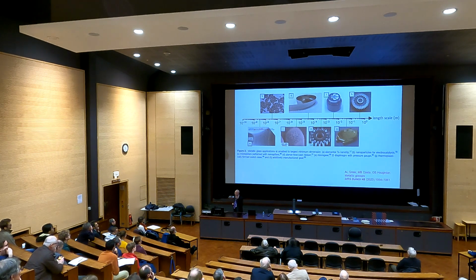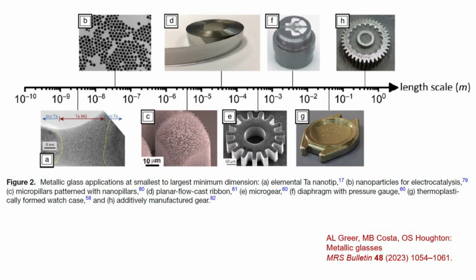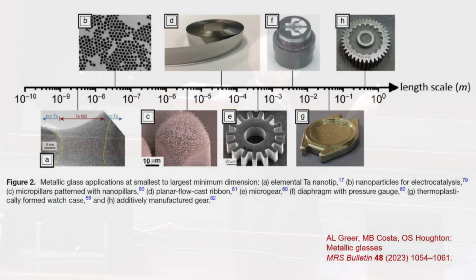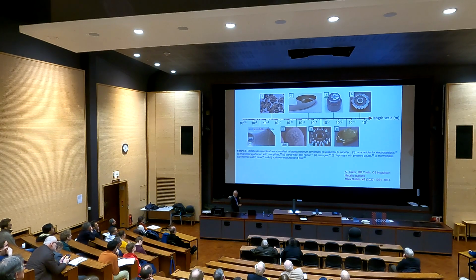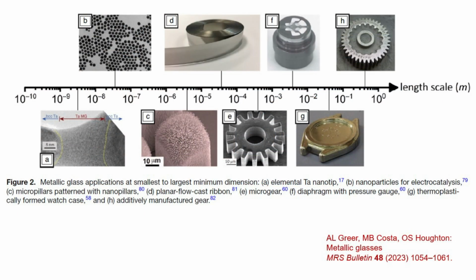I'll close the talk with a series of quick slides to give you an idea of where's the world of metallic glasses right now. So it started with thin ribbons. Those are the million degrees per second ribbons that are used in the transformer core. There was interest in going finer. This is a pure metal glass made at nano tips, and the cooling rate of that is about 10 to the 14 Kelvin per second, so 100 trillion degrees per second.